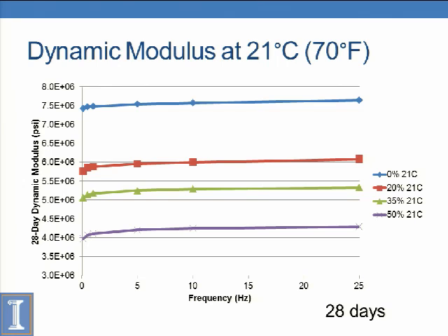For this test, we adopted the hot mix asphalt dynamic modulus test you guys do. We took a normal 4x8 cylinder, cut 1 inch off the top and bottom, so it was the typical 4x6 specimen size, and then tested at dynamic modulus.